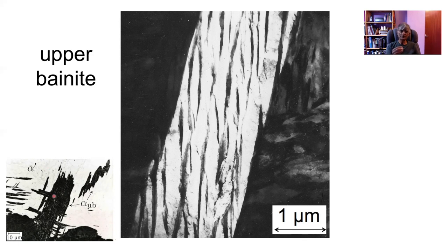Whereas if you look at the detail inside this, then there are thousands and thousands of tiny platelets, only a quarter of a micrometer in thickness, and lots of interfaces between either the cementite or any other residual phase between these platelets, which are attacked by the etchant. And therefore, the bainite appears darker than the surrounding matrix, okay? So optical microscopy cannot reveal the detail that we are interested in. Notice also the lenticular shape and sharp tips over here, everything pointing towards a displacive transformation mechanism.